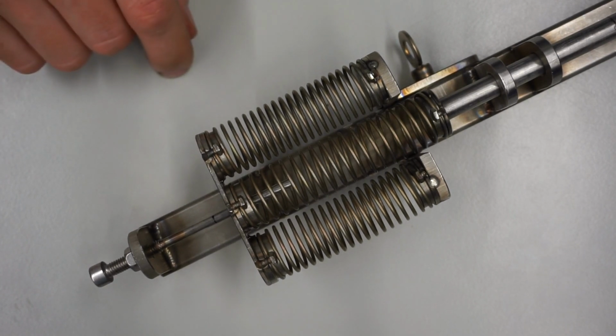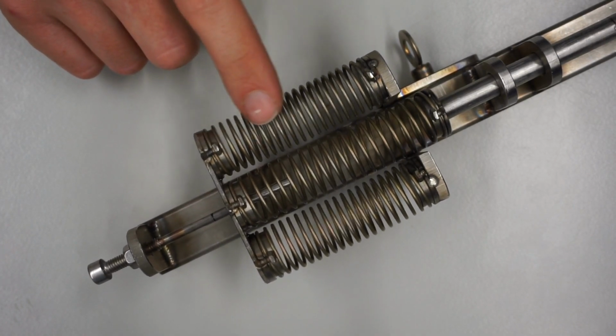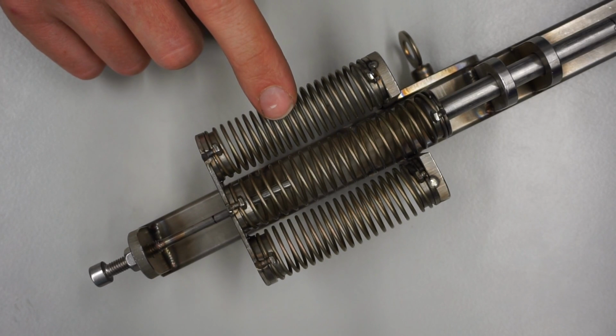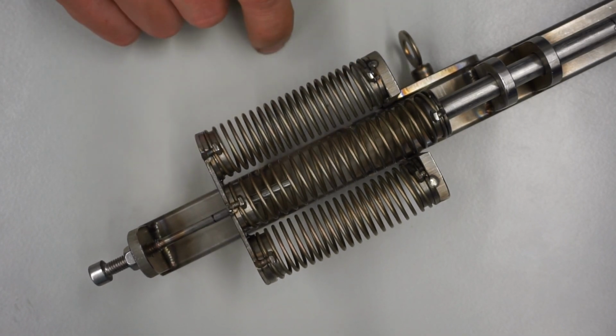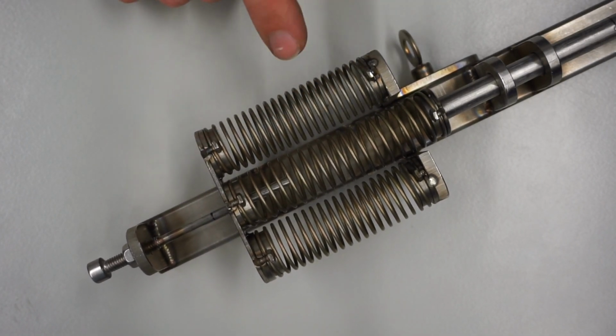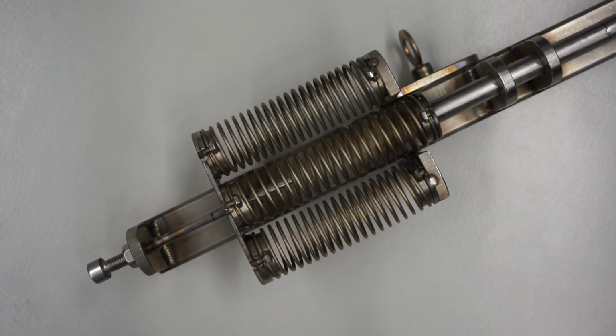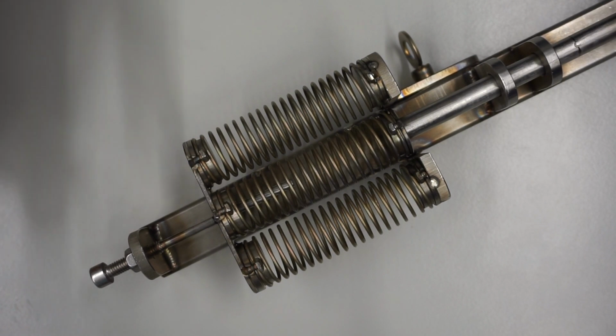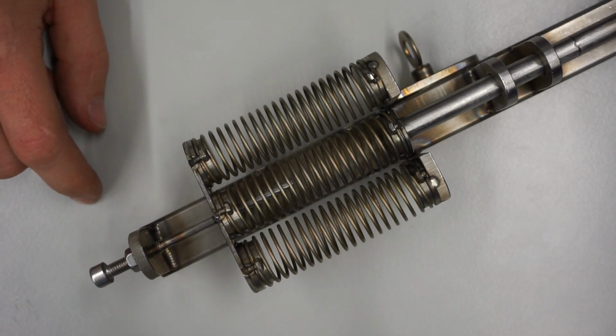If you recall that the hacksaw got stuck in the outer bar earlier, this clearly shows why. The outer bars are compressed, and if we cut a slot through them, the slot tries to close on us. And this brings us to the last point of this episode: springing back distortion of welded workpieces due to post-weld machining or post-weld heat treatments.